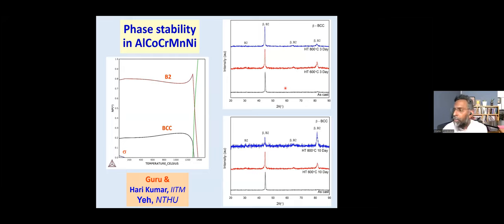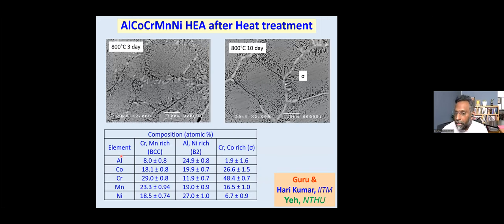This is another system where I have taken the same four-component alloy, added aluminum now instead of adding copper. The moment I add aluminum, you get a BCC structure or a B2 structure, which is an ordered BCC kind of structure. Again, we say that there is a low temperature sigma phase here, which is shown, whereas your actual XRD patterns do not show anything like that. And if you actually do heat treatments, there is a possibility of getting a small sigma phase.